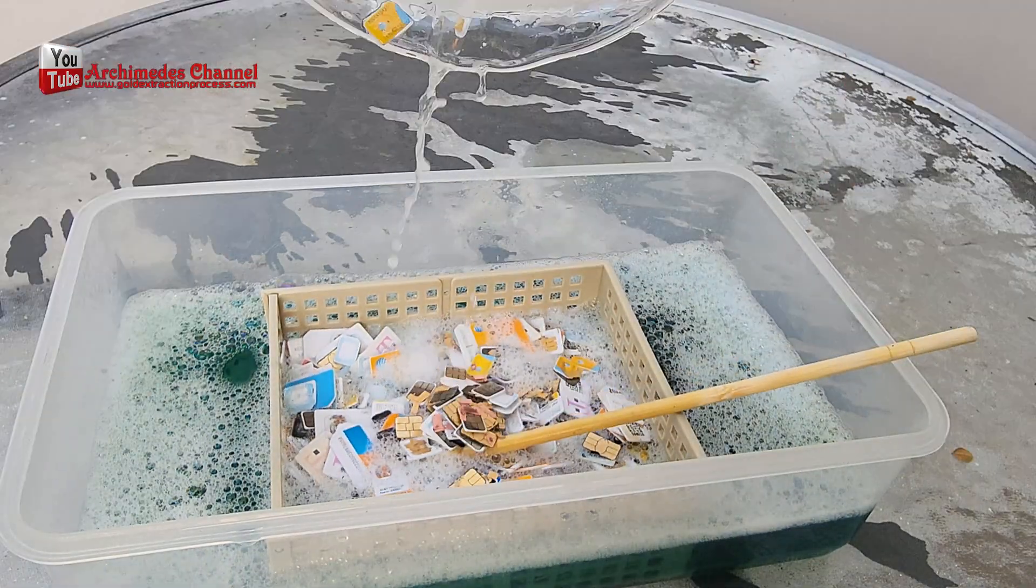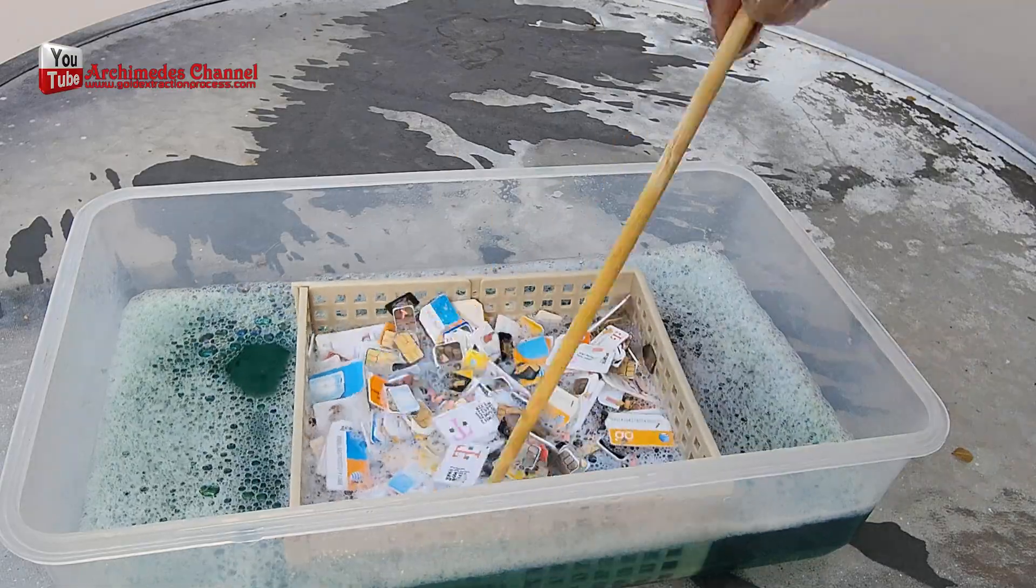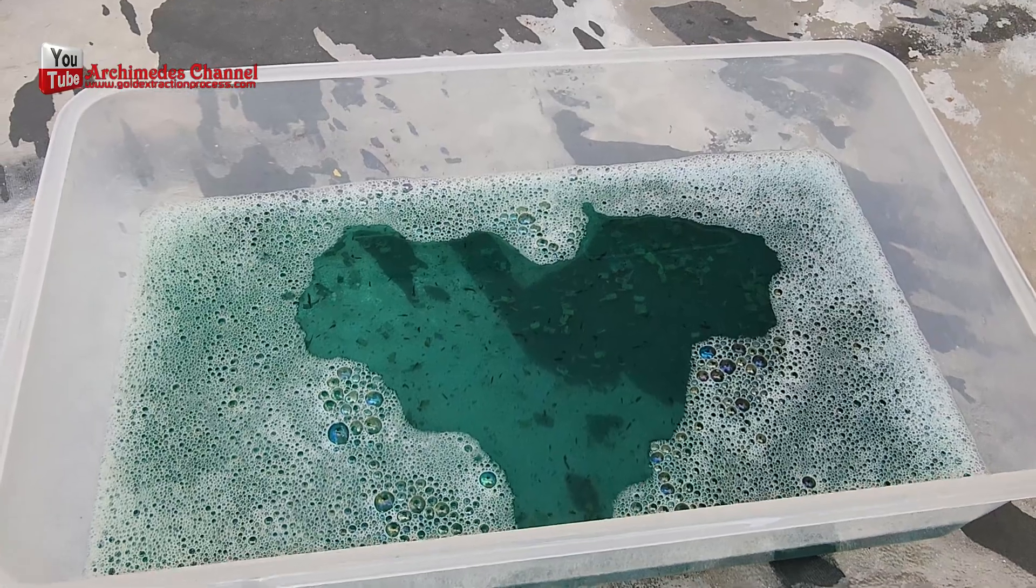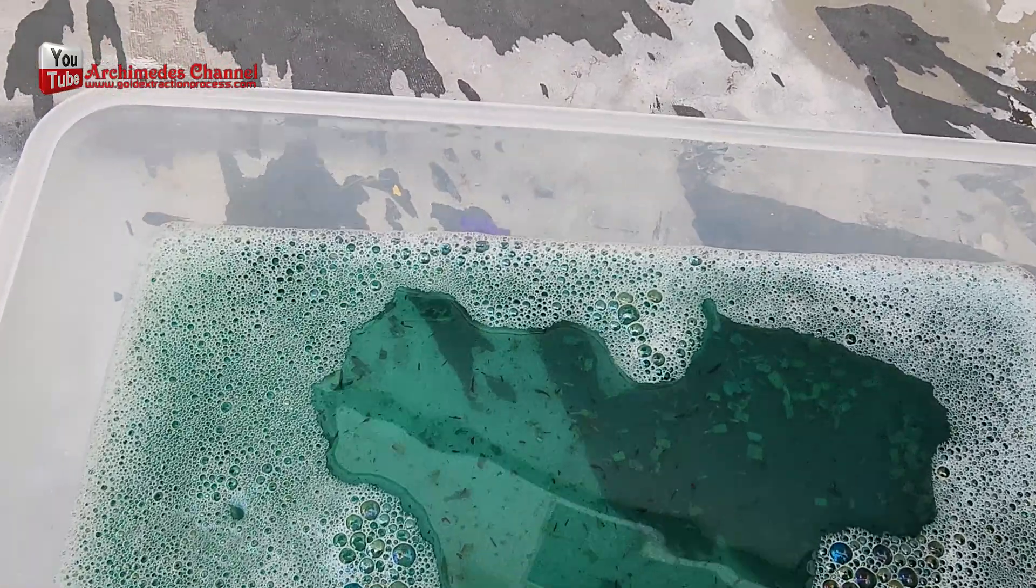In actual practice, I had to do this twice because I used too little toilet cleaner and the gold plated on the SIM card wouldn't come off completely due to the acid saturation.